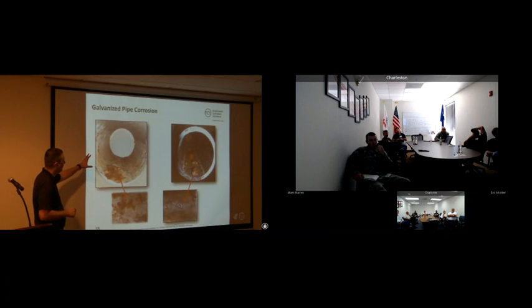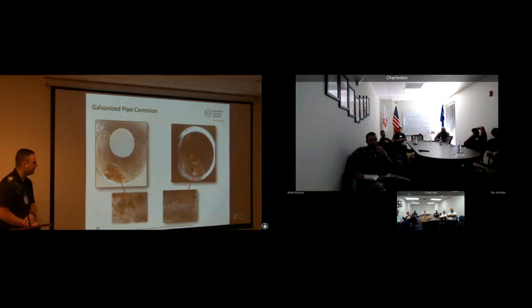This is what it looks like. So you can see orange in these pictures, that's our iron oxide. We take the 2 pieces of pipe at the top and we clean them up and we look at the bottom, especially the bottom right, you can see how aggressive that oxygen corrosion was on those breaches in the zinc coating. So the zinc coating, once it's breached, you can have failures in a matter of months. That top left picture, you can see there was a water line in there about a little over halfway up. So that's why you see all that white, fluffy, powdery stuff. That was the zinc coming off the side of the pipe.